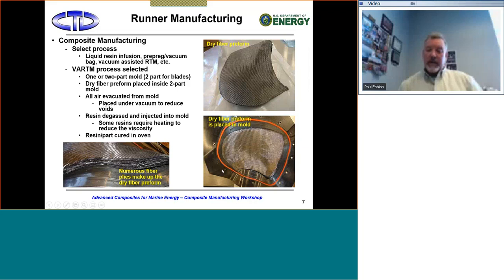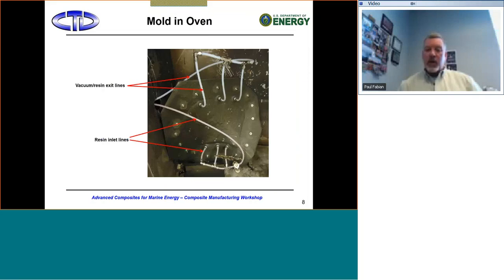And so then the lower right photo shows the dry fiber preform inside the mold. That's 1/2 of the mold there, and you see that there's a silicone rubber gasket that goes around the blade, and that maintains the vacuum seal when we do the impregnation. So then moving on, once you close up the mold, you have to plumb it. And in this case, we have 3 different resin inlets, usually located on the bottom. So you have a resin inlet line that comes down to a manifold. And then you also have vacuum and or resin exit ports that come out. This is where you're actively pulling vacuum, in this case to degas the dry fiber preform.